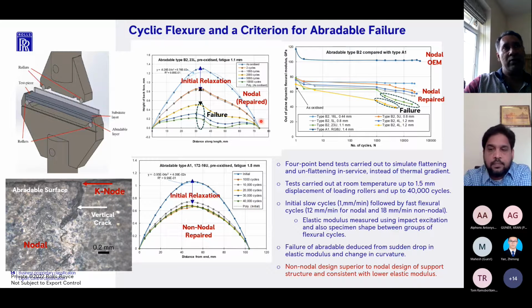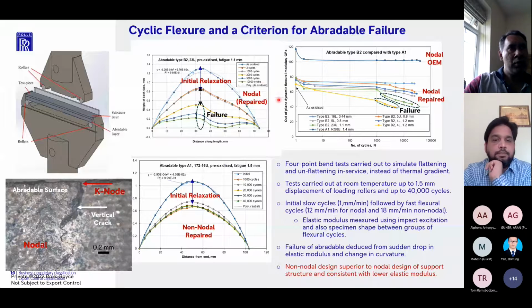So effectively, you do a number of cycles, take the specimen out, measure the shape of the specimen, measure the elastic modulus using resonance, inspect the side walls, then put the test piece back again, do a few more thousand cycles, again take it out and repeat the procedure. What you can see is that